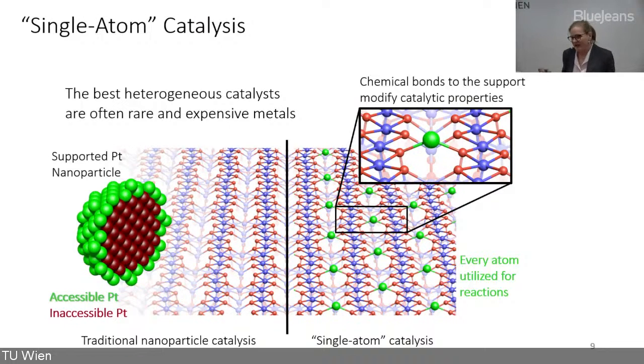And it's a sad truth that the best heterogeneous catalysts are often rare and expensive metals, such as platinum. So the idea is that if you could disperse it to single atoms and put it on a surface, then maybe a single atom could be responsible for this reaction. First of all, you need much less of the expensive material, but also the single atom is then very intimately related to the support. So it will really matter how the single atom binds to the surface, and the environment of the single atom on top of the support really matters.